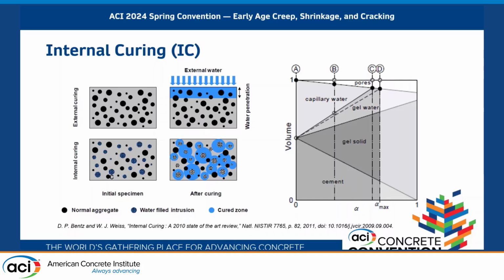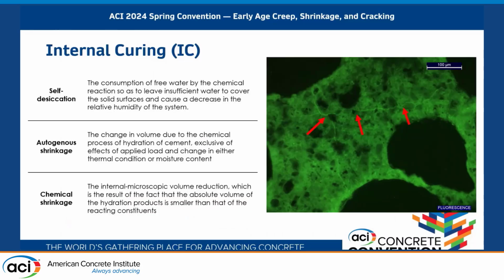For several reasons, not only the drying or shrinkage that can occur, but also the effect of self-desiccation and just the creation of hydration products that have a lower volume than the unhydrated materials. So some of the concepts that were touched on in the report are, as I mentioned, self-desiccation, when the material by its own reaction is starving itself from water. It can lead to, in some extreme cases, cracking.